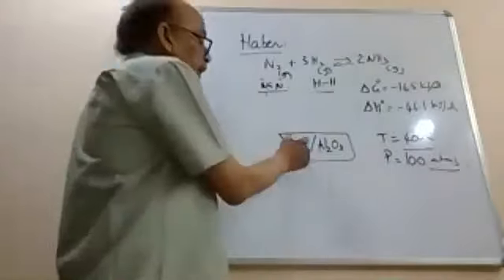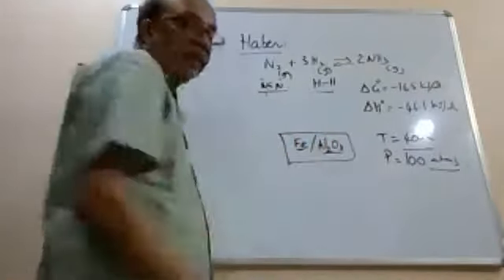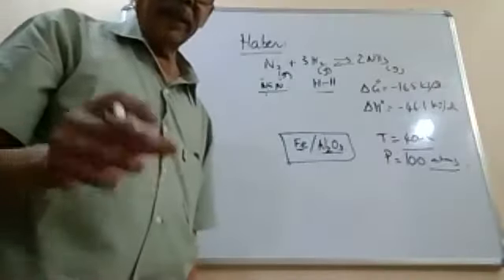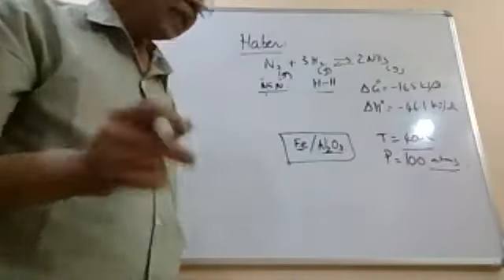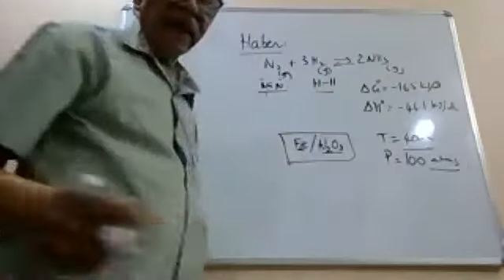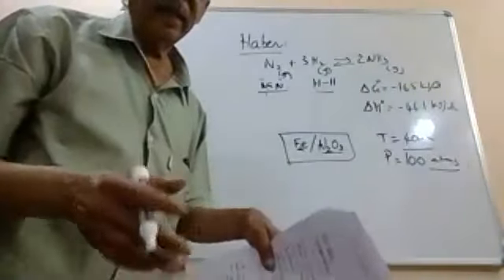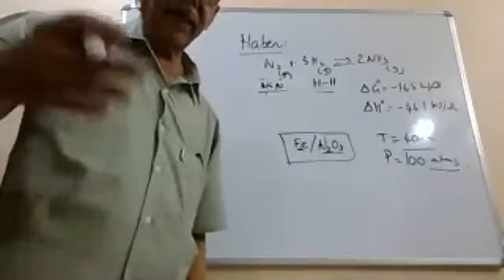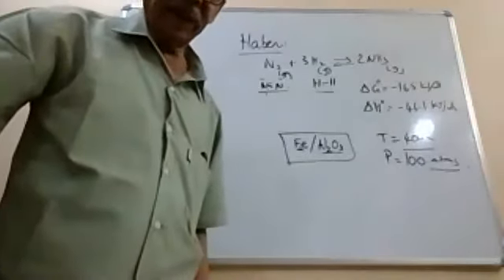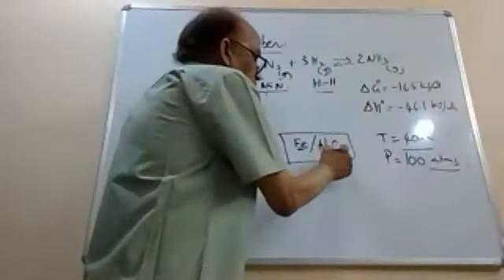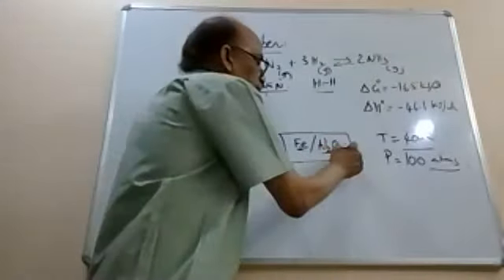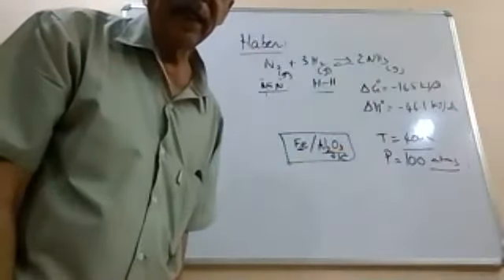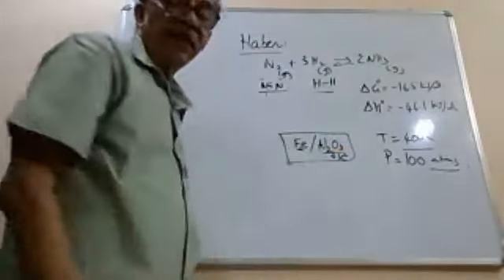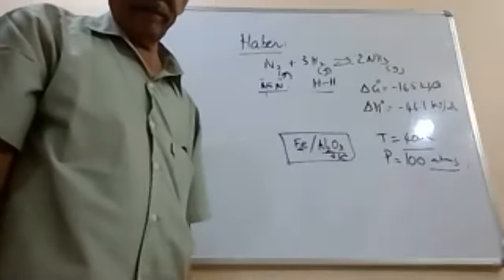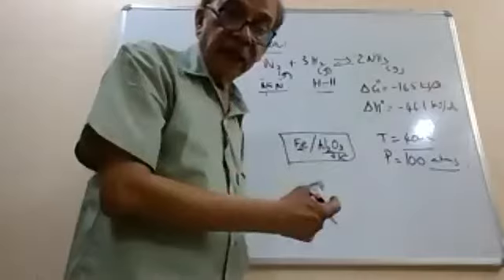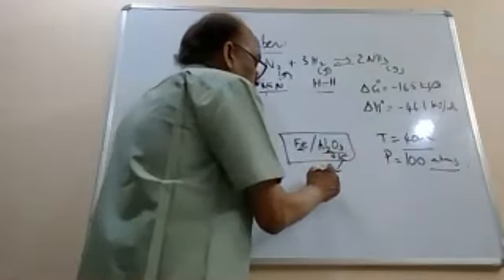So since you can't tweak the iron, people started tweaking aluminum oxide. The aluminum oxide here is a support. What this basically does is it does not allow the iron to congregate and make bulk iron. It kind of keeps the iron separated. That's the job of an anchor. However, when you put small amounts of potassium into aluminum oxide, it tremendously improves the catalytic efficiency of the iron. So these are all secondary interactions. So in this case, the potassium is called a promoter.